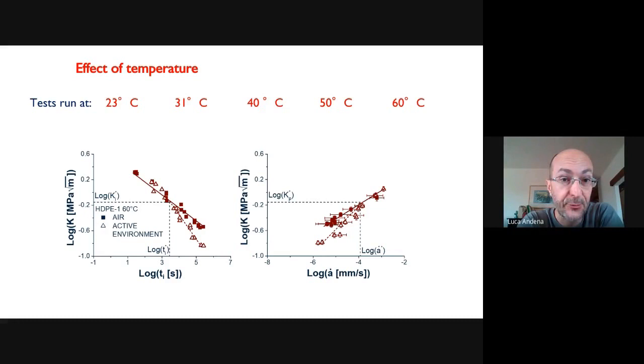Temperature is used frequently in environmental stress cracking testing because tests can take quite a long time. So you typically use a temperature to accelerate the tests, which works fine as long as the increase in temperature does not change the activity of the medium, of course. Up to 60 degrees, typically things are not severely affected.